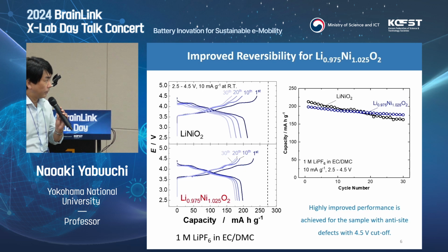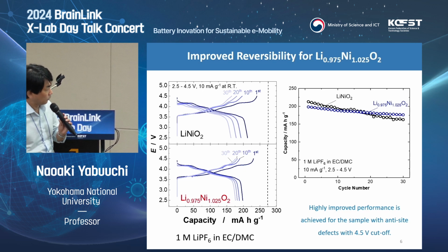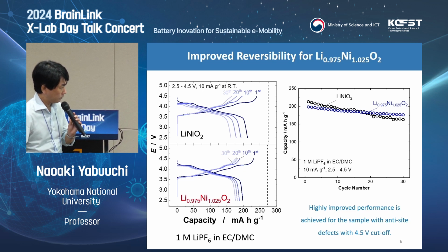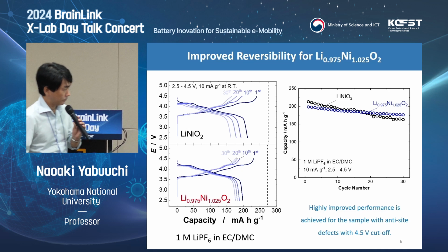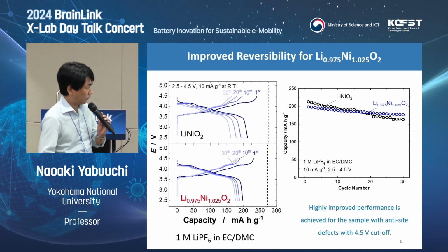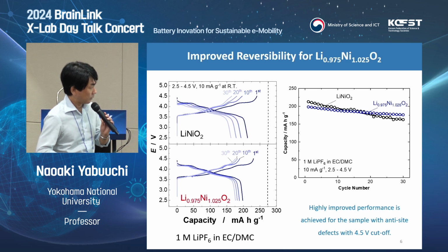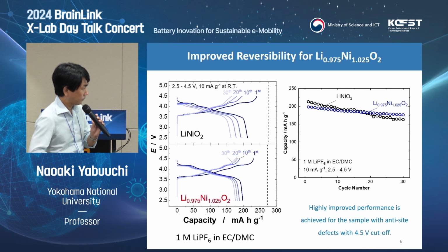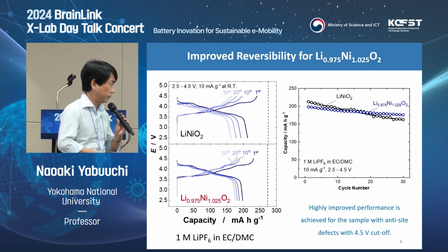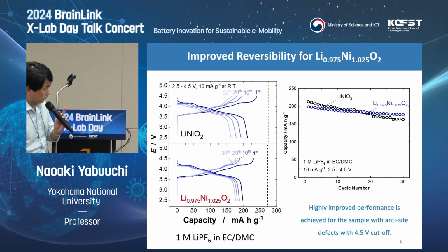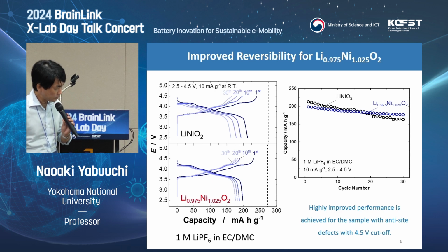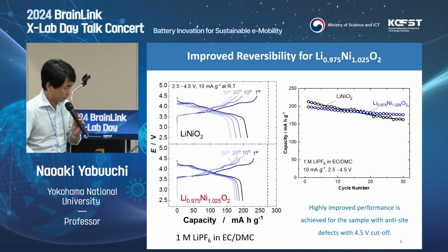Here you can see a comparison of the charge and discharge curves for stoichiometric lithium nickel oxide and lithium-deficient nickel oxide. The reversible capacity is slightly lower for the lithium-deficient sample, as you would expect. However, the cyclability is much better. After 30 cycles, the capacity is larger, and when you look at the high voltage region, you can see much improved reversibility. This is the result with a conventional electrolyte solution.